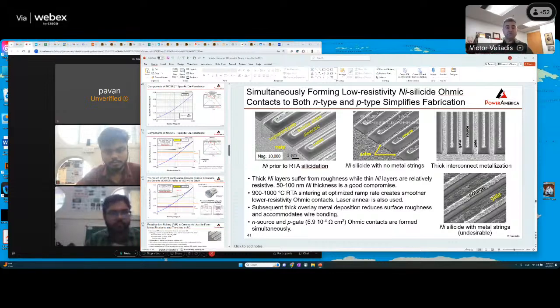You drop it from 350, you take it down to about 100 micron, and then at that point, you've got the surface in the back, you put a nickel layer, just blanket nickel deposition, and then you come with the laser anneal. Because if at that point you do an RTA, then the whole wafer will get to 1300 degrees and you will destroy all the ohmic contacts you made in the front. Okay, so that's where the laser anneal comes in.